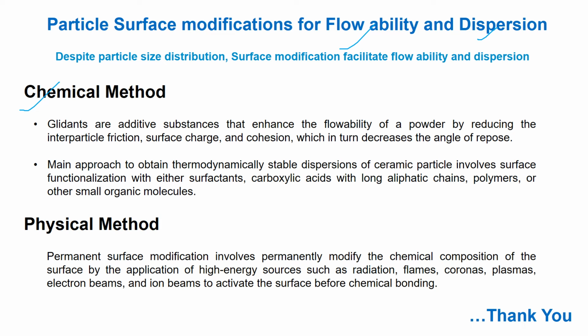Glidants like silica sol are additive substances that enhance the flowability of a powder by reducing the interparticle friction, surface charge and cohesion, which in turn decreases the angle of repose. The main approach to obtain thermodynamically stable dispersion of ceramic particles involves surface functionalization with surfactants, carboxylic acids with long aliphatic chains, polymers or other small organic molecules.